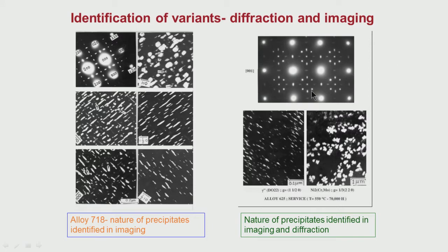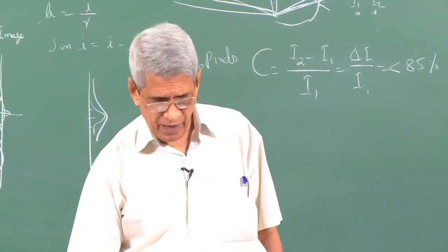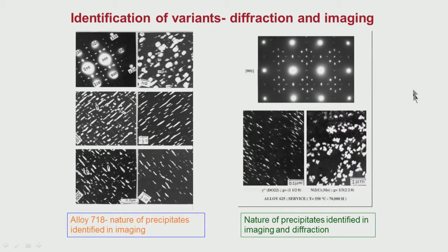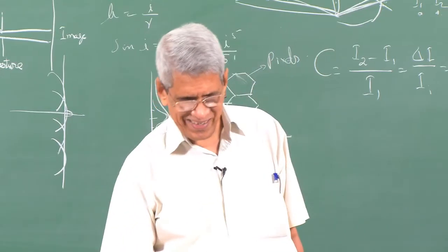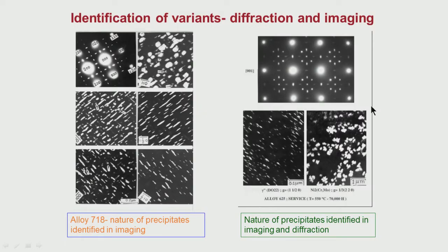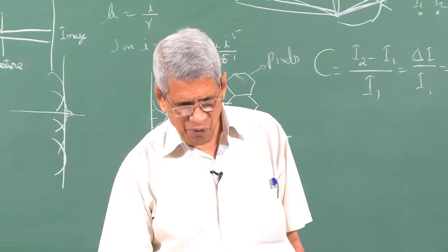In this particular case, I am gradually increasing the complexity of the diffraction pattern. Here after analysis, we find that there are two types of precipitates. Putting apertures around different super lattice reflections, I could identify the various types of precipitates and how they are distributed. It is easier said than done, because it takes a lot of effort to analyze this pattern. Normally when we get a pattern like this, we put apertures around it and get the images and then do the analysis later. That is what is being done, but the whole thing takes quite a bit of time.